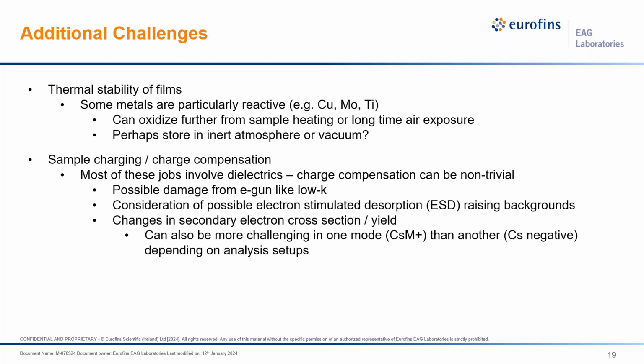Also, practical considerations include sample charging. When we have to employ charge compensation, we do that by using an electron beam. But the electron beam itself could also damage some material. So for example, low K films, which are very porous, tend to collapse under the E-gun. Another thing that can happen is that some atoms may actually be desorbed from the surface by the electrons. This is what's called electron stimulated desorption. This can raise the backgrounds for measuring things such as carbon and hydrogen, for example.